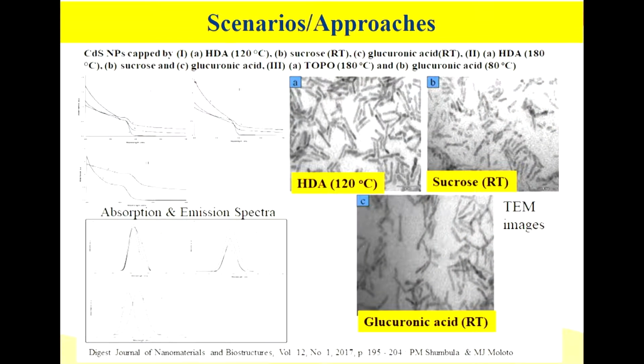And this is another example where we've used the same approach, just to demonstrate that if you're preparing this in a normal HDA-based environment, which is hexadecylamine-based and normally used a lot in the single source approach, the moment you start replacing the HDA with sucrose or glucuronic acid, the particles remain with the same shape, except that to some extent sucrose is not as robust in capping or stabilizing the nanoparticles, such that the particles break a little bit and the shape becomes affected.